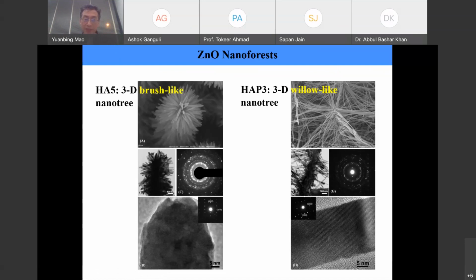So definitely they are crystalline, and these two high-resolution TEM images are from the branches. Of course, it is difficult to get high-resolution TEM images of the original zinc oxide nanowires. So these focus on the branches, and you can see that they are single crystalline, and they all grow along the 002 direction. So that gave us a pretty good idea.